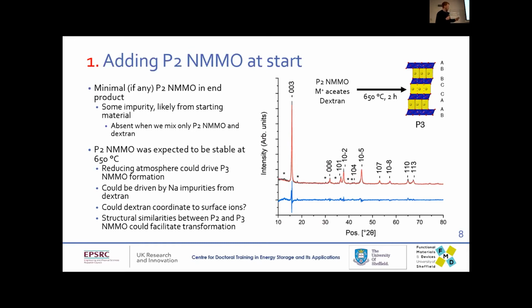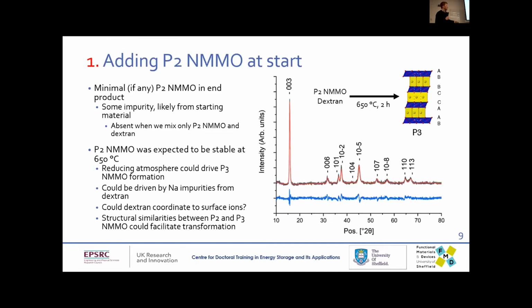So there's a couple of reasons that might be the case. I've listed them here. I've run the same experiment except without the metal acetate, so just mixing P2 and dextran in water and calcining that, and we get the same result. We get a purely P3 structure. So it could be reducing atmosphere from dextran. It could be sodium impurities from dextran. I'm not sure that's the case. It could be dextran coordinating surface ions, which would be really interesting because then it means we can use dextran as an aqueous binder, similar to Sylvia's work that we talked about yesterday.